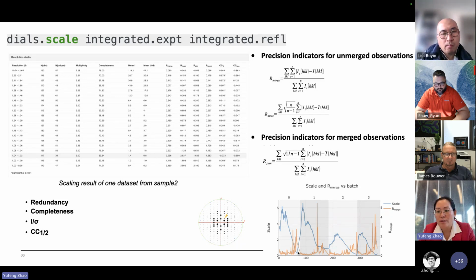Normally for a data set, the first few images are not very good, maybe because the signal is not strong enough or something else. And the last few images normally have high radiation damage, so we don't want those data, as they would damage our result. We go through the whole output and use CC half to decide the resolution cutoff. Typically we cut off around 0.3. We can also use CCP4 to open the reflection file to visualize the intensity spread and see if it makes sense or not.